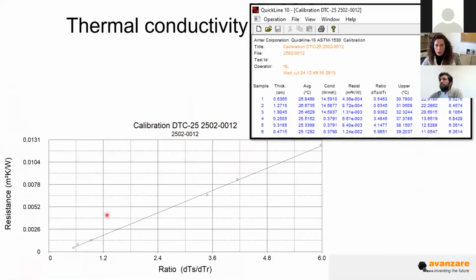So how does this apparatus work? It works with standards made of stainless steel and Vespel, which is a plastic, a polymer with perfectly known thermal conductivity. So with standards of different thickness, we can build this calibration curve. And in this calibration curve, we insert the results of our samples to determine the resistance and, knowing the thickness, the thermal conductivity.